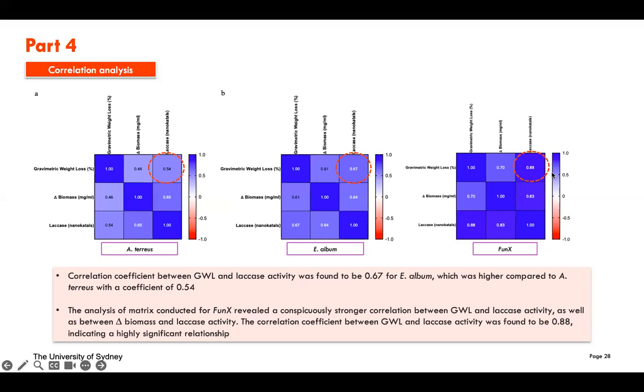So we can conclude here that the higher the laccase produced, the more weight loss can be caused on the polypropylene. And we can also see that the relationship between the biomass and laccase is also highest in the new fungal isolate. It shows that the higher the biomass, the more laccase activity could be observed, right?